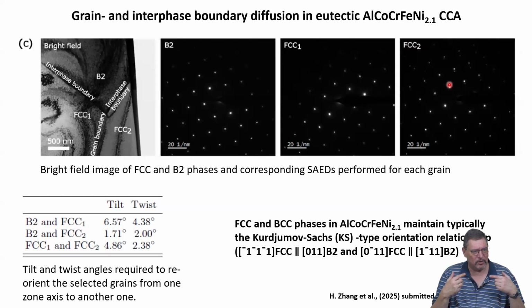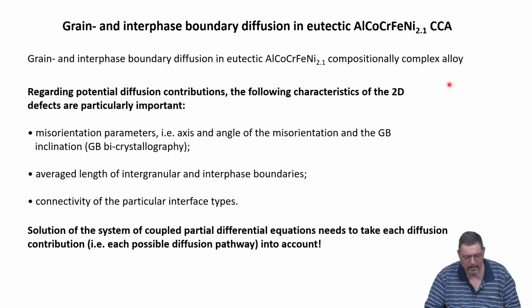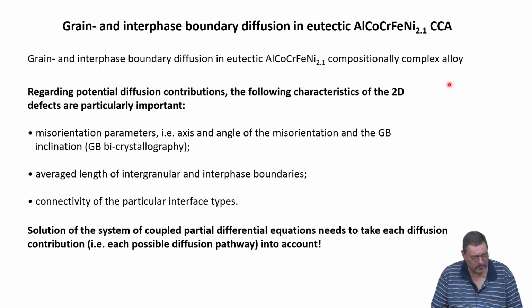And this will be important because these two types of interfaces have very different diffusivities. One being very ordered, one would expect diffusivity is low, and one being disordered, giving rise to enhanced diffusion along that interface. So, the following defects are important. Misorientation parameters, like which axis and angle of the misorientation we would have, and also the grain boundary inclination is a very important aspect of this. Especially also the average length of all these grain boundaries as well as the interface boundary and the connectivity. So is it a percolating pathway or is it not a percolating pathway is of large importance.